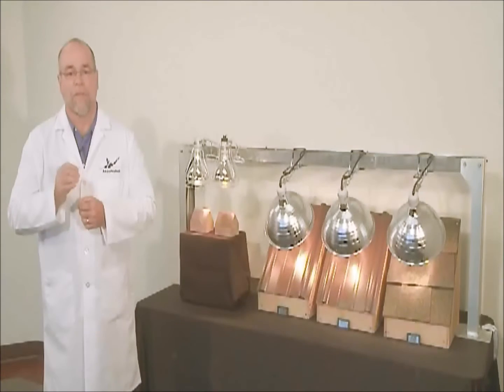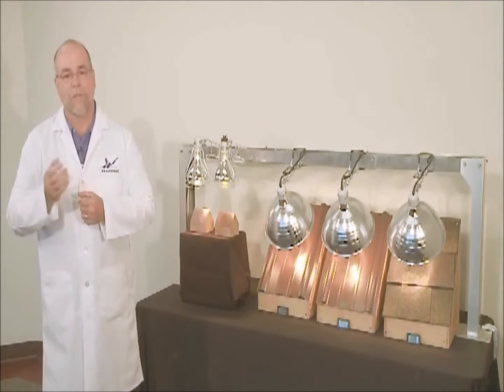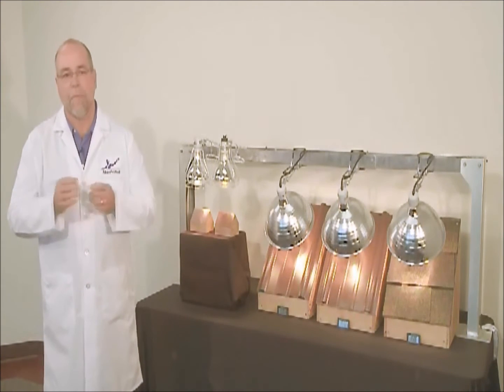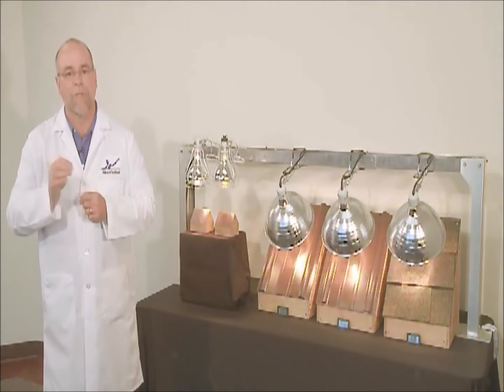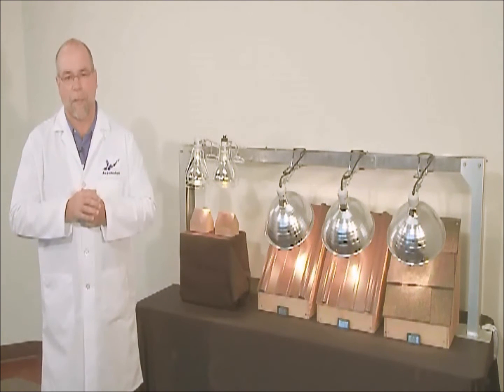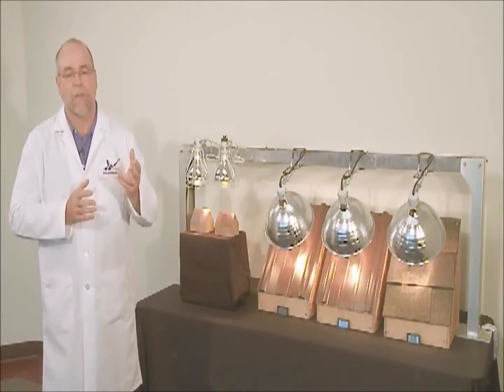pigmentation dark brown. For the next demonstration, we will look at the improvement in solar reflectance between a Cool Chemistry Series sample and a standard pigmentation version. Both are the same color, but have different solar reflectance values. The sample on the left is a Cool Chemistry version, which has a solar reflectance of 0.28. That means that of all the solar energy that hits this, 28% of it is reflected off and never absorbed. The sample on the right uses standard pigmentation, same color, but only has a solar reflectance of 0.13. So in this case, 13% of all the solar energy that hits it is reflected. In this example, we have two pieces of the same color, but one is more than twice as effective in terms of energy efficiency.